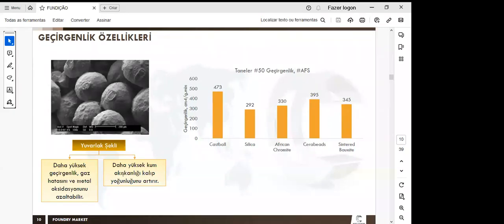This type of shape in rounded grain sands provides high permeability, where we can reduce defects associated with trapped gas. And the second advantage is a higher sand flowability, increasing the mold density. The graph shows a comparison of the permeability results of the sands used in foundries. The tests were carried out according to AFS procedures, and only the grains retained between the 40 and 50 meshes were tested. We can see the high permeability of the Castball.